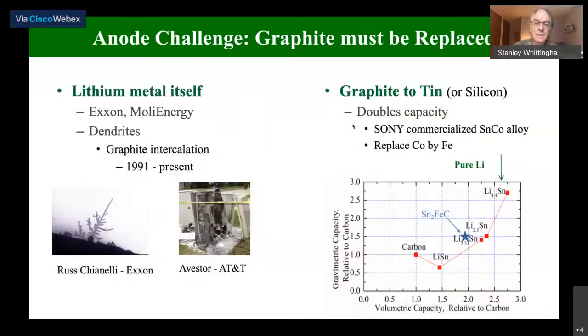Let me mention the anode briefly. As I said, we started with lithium. Exxon and Moly Energy, where Jeff Dahn was, also used lithium. This tends to form dendrites. And these are some dendrites that Russ Chianelli, who was at Exxon, showed using in situ measurements just with an optical microscope.